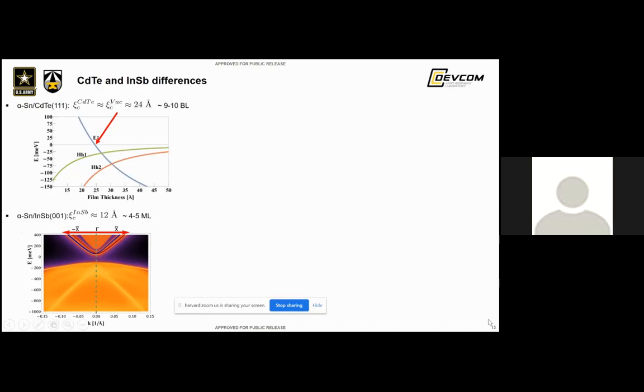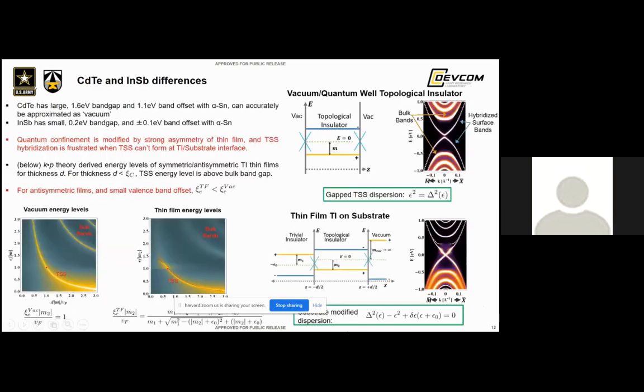Now, there's a theorem which George DeCosta came up with, which shows this nicely. I don't fully understand this, so I won't go into the details here. I think George understands it best. But basically, he can show that those two effects combine to make the critical thickness more than what you'd expect if you confine the material in a vacuum model, for instance, vacuum on both sides. And so that effect, I think, is primarily the quantum confinement